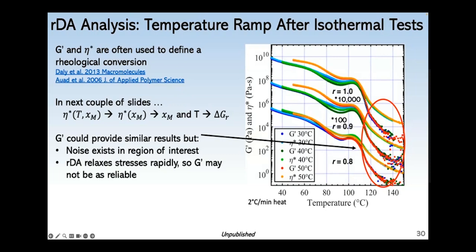And now I'll be moving on to the retro Diels-Alder analysis. In the next couple of slides, I'll show how I went about this one way and then a second method. But in this first method, I started off by ramping the same samples from the isothermal rheology up to a high temperature, as I show in this plot here on the right, where the complex viscosity is in the lighter colors and sits atop G prime in the darker colors.